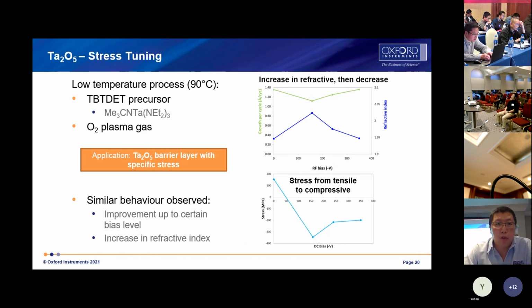Tantalum oxide is usually used as a barrier layer. It can also be deposited at a lower temperature, 90 degrees. Film stress can be adjusted by bias power. There is tensile stress without any bias power. With bias power, the stress becomes compressive. You can see the data.